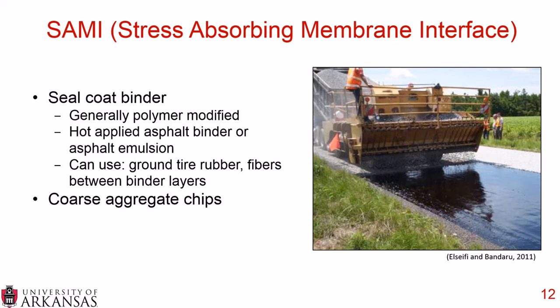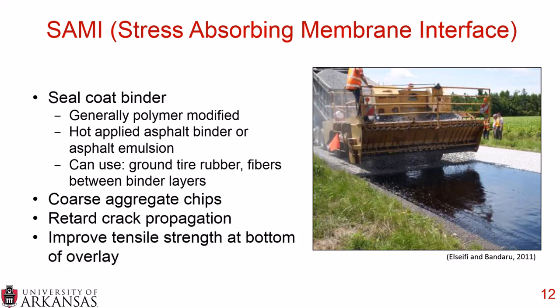You put a pneumatic tire roller over it, you orient the particles, you sweep it, you let it sit for probably about a week to make sure all the water has left the system, and then you place your overlay. And these SAMIs retard crack propagation, and it also improves the tensile strength at the bottom of the overlay.